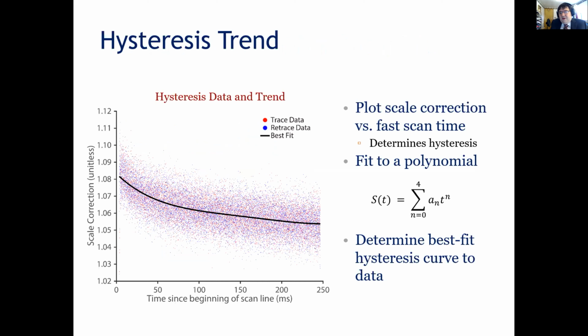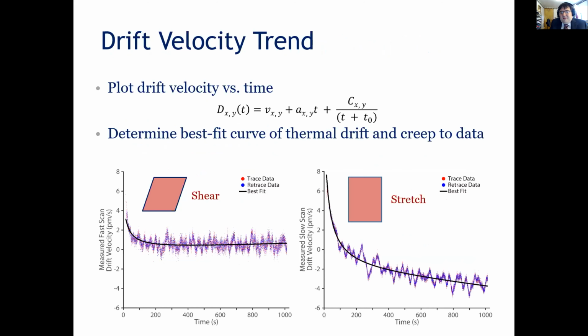And we can plot that versus time and get a trend line for that, and there's the distortion that's affecting our image. This is scale correction versus fast scan time, which is a fit for hysteresis. So we used a fourth degree polynomial as a model for our hysteresis, which fit pretty well to the data. Then we also have fast scan drift velocity, which causes shear, and slow scan drift velocity, which causes stretch. And we fit those to our data using some models for drift velocity and creep with a tiny little bit of acceleration, and that also fits excellently.